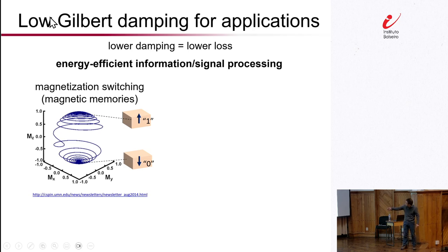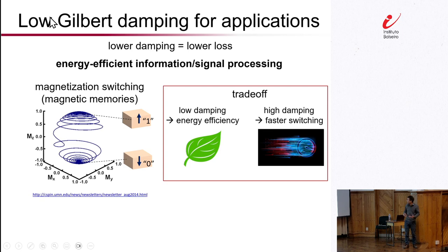Now, the way in which the magnetization switches, it actually does not take a direct path. It takes a long, spiraling pathway from one direction to the other. If we have a low damping material, we can start this kind of spiraling dynamics with a lower amount of power input. So in other words, by achieving low damping, we can have a magnetic memory that operates with better energy efficiency.